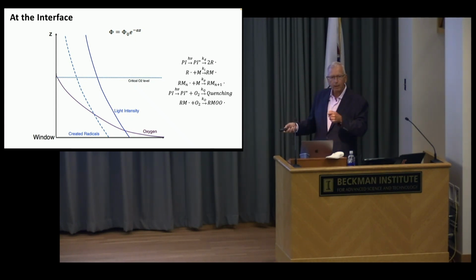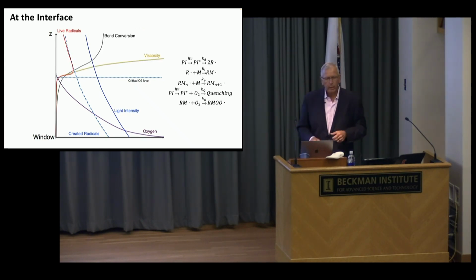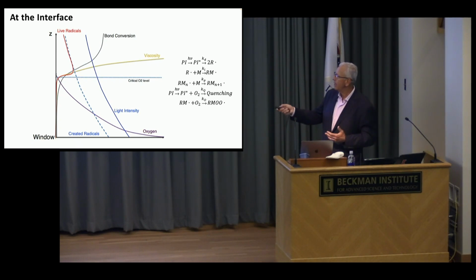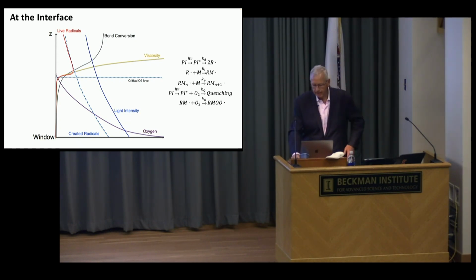Well, here, that radical is consuming the oxygen. But we have an asymmetric way of replenishing the oxygen. There's a chemical equilibrium that's trying to be reestablished, and we have a gas permeable membrane. Oxygen's coming back in the Z direction. But as the oxygen concentration decreases as a function of distance, we get below a certain threshold and a polymerization will take place. And if it's a cross-linking system, molecular weight will go to infinity. There's a polymerization gradient happening, but this is the dead zone that we study, that distance.